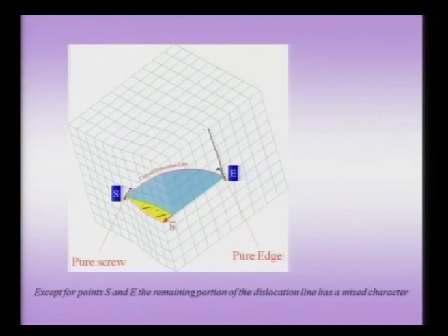So clearly, you can see that this curved dislocation line has one terminal point E, wherein you can visualize the extra half plane. The other point, which is purely screw, has shear fields, that means it has the shearing pattern which is very characteristic of screw dislocation. If you concentrate on this corner, it is like pushing in one part of the crystal with respect to the other, and therefore that edge character is reflected here, the pushing in part. But if you look at this region, it is more like a shearing part, where I have sheared this crystal, and therefore this is the screw part.